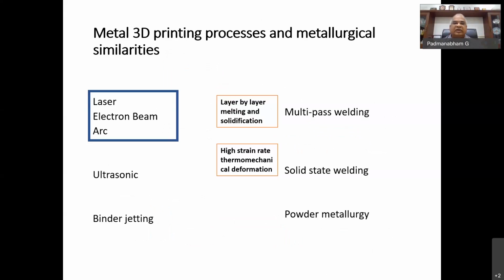Now, if we consolidate these three methods that I have mentioned for additive manufacturing and compare them with the technologies that we are already familiar with in manufacturing. Let us say the laser additive manufacturing or electron beam AM or using welding arc additive manufacturing to make layer by layer melting and solidification. It is similar to multi-pass welding. The ultrasonic method that I have mentioned is similar to solid state welding. It is high strain rate thermomechanical deformation. And the binder jetting method, there also we are making a shape and making a green component using a binder, then debinding it and then sintering it and getting a component. Same as we do in powder metallurgy.